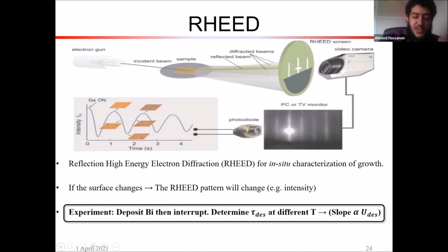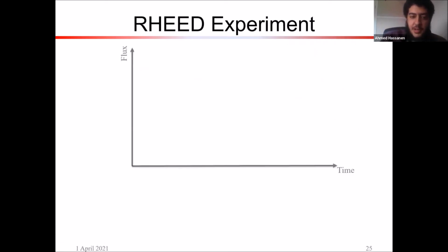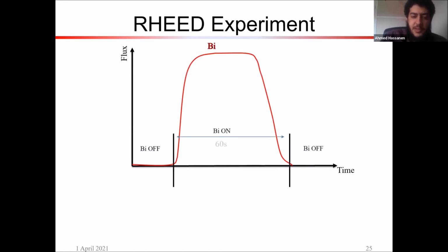And so basically the gist of the experiment is that we want to deposit bismuth and then interrupt the growth. As the RHEED changes, we can determine the tau desorption for that particular temperature, then we can extract the slope. To elucidate a bit more on how this experiment went, this is a graph of the flux versus time for bismuth. We can see here, first we have our gallium arsenide sample with bismuth off. Then we're going to start bismuth for 60 seconds to make sure it covers the surface. Then we're going to have bismuth off.